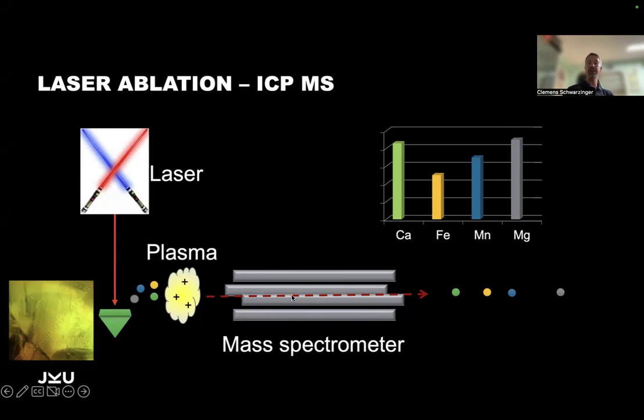So what it does now, it separates our elements by their weight, like calcium, iron, manganese, and magnesium. And then we have a detector, and the detector detects how much of each of these elements is present. And then at the end, we end up with a table. I just plotted here 4 elements. Currently, we're running about 35 to 40 elements in a single run in 30 seconds. We have all these elements just to make trace element analysis and to collect data in the first place.